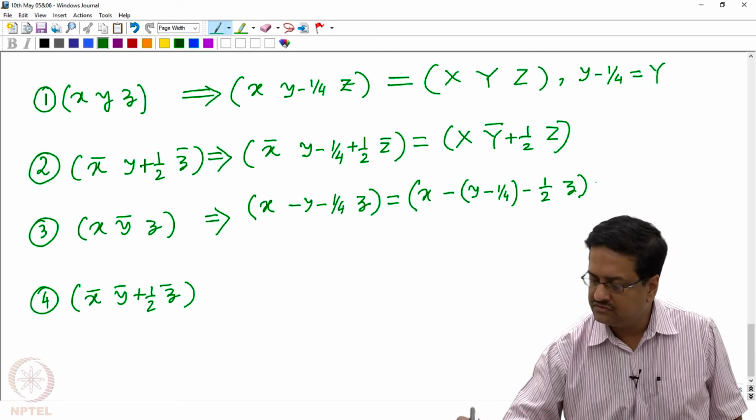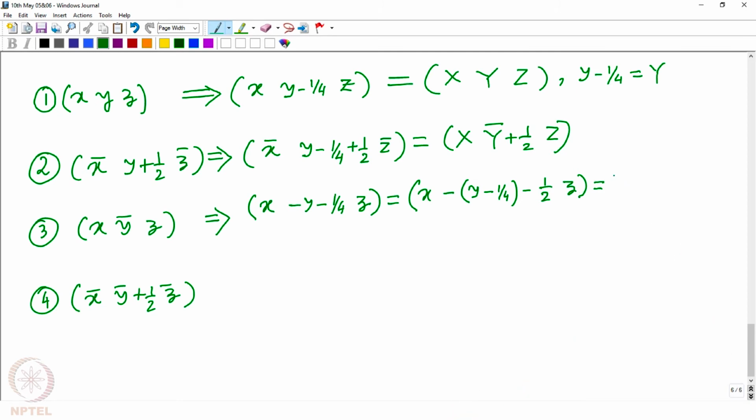So that means now we can write x, y bar minus half, z, and as I said, now on y I have minus half, which means it is outside the unit cell. So to bring it inside the unit cell, I rewrite it as x, y bar plus half, z by adding 1 along the y axis only.